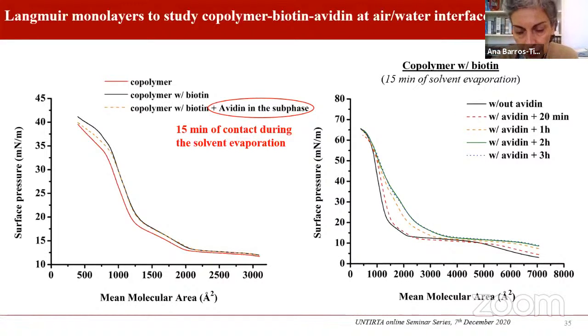So we decided to assess this using longer times. And it proved that actually the interaction between the bioanalyte and the bioreceptor, so between biotin and avidin, is time dependent. And if we allow more time of contact between the monolayer and the avidin in the subphase, the isotherm that we observe is pretty different after 1 hour. So the tests we had done originally using 15 minutes were really very short to get any conclusion. But if we allow at least 1 hour, we can see that really avidin tends to interact with the biotin as expected.